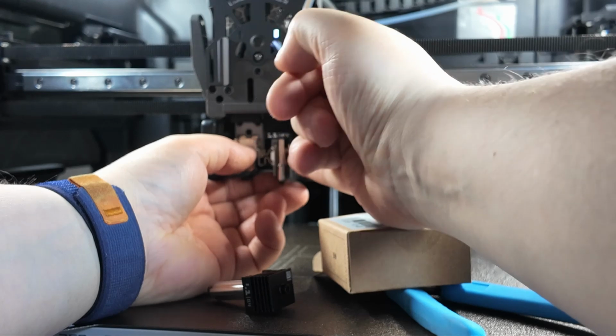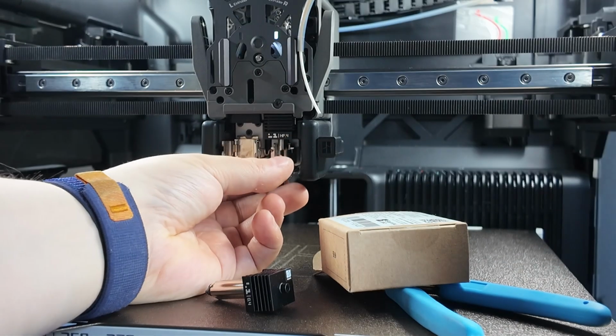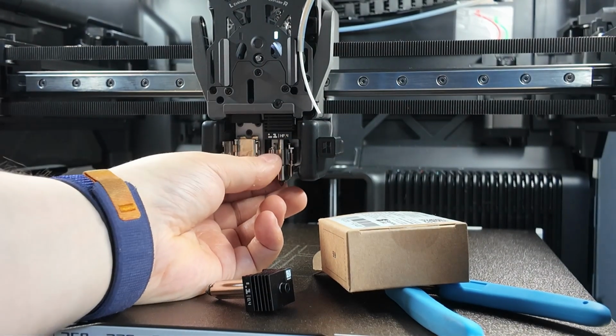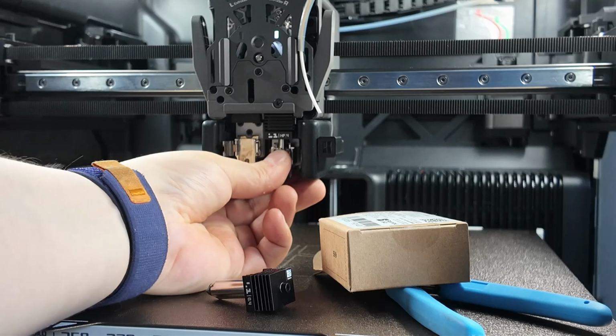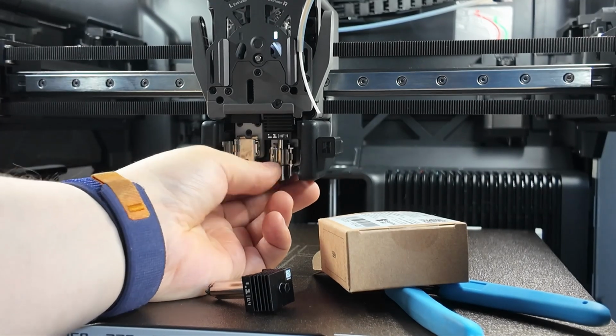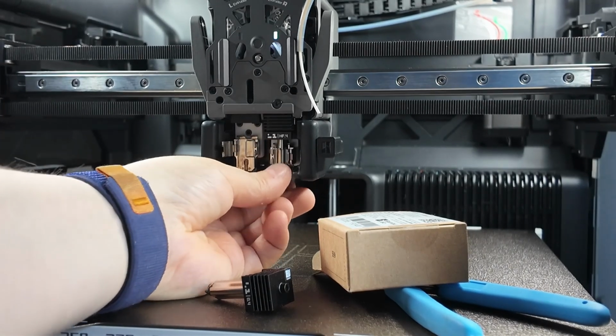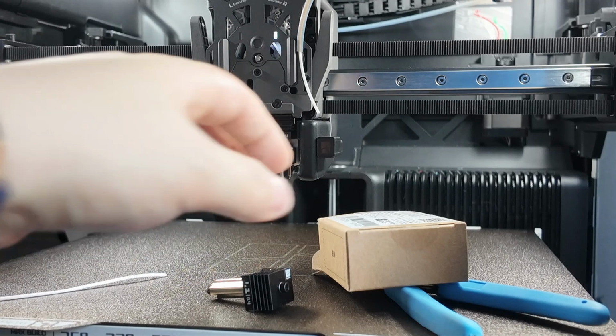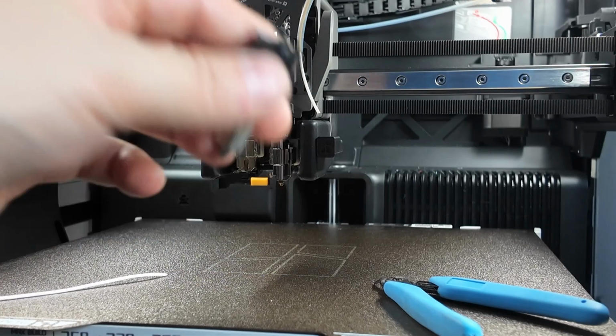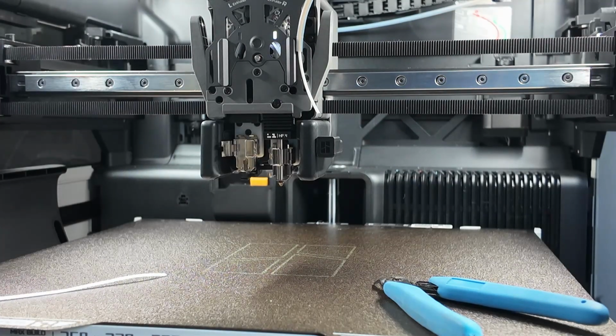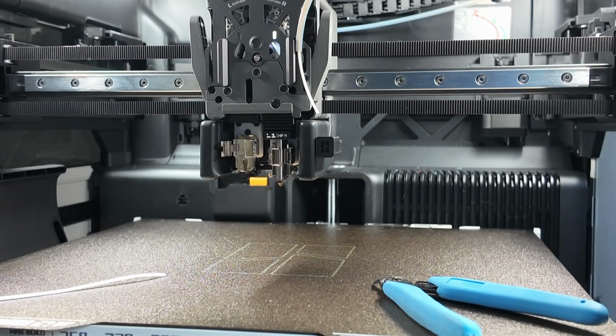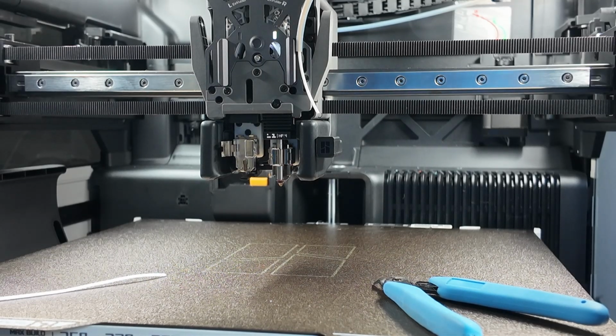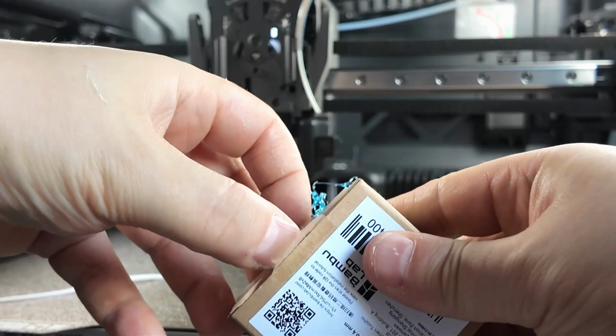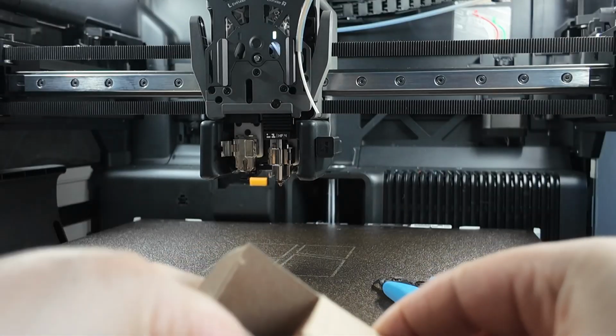Go into your filament settings and just increase the max volumetric speed to suit your printer and material. For most PLA filaments, don't go above 50 cubic millimeters per second. That's the practical upper limit for the high flow nozzles. And if you're pushing your flow rates up, make sure to increase your nozzle temperature by 5 to 10 degrees Celsius for better consistency and fewer jams.